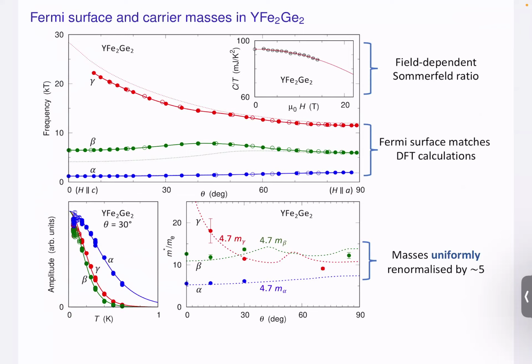The point was that all of these follow quite closely what you would expect from DFT calculations. The dotted lines are the DFT results, just from the picture I showed in the beginning, and the dots are the measured data. So basically, we're fine. You may even ask, why did you bother with this experiment? You spent so much money on liquid helium to measure this, and then we just see what we could have got from a few hours of computer time. But the point is that the calculation doesn't tell us the mass correctly, right? Sorry, the calculation tells us 70 millijoules, and we need to get to 100.